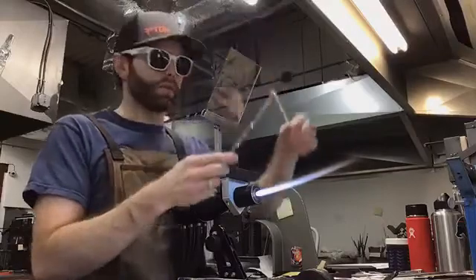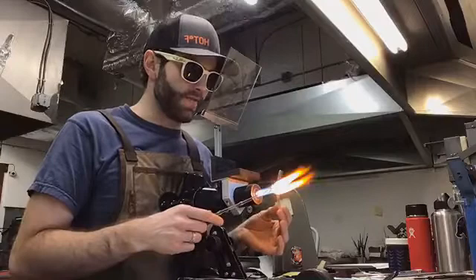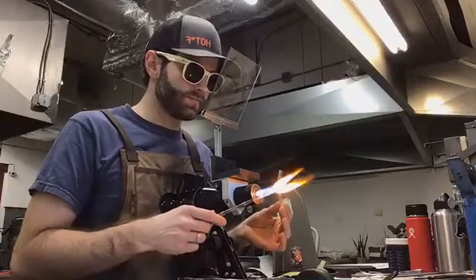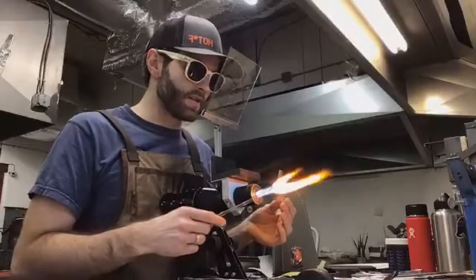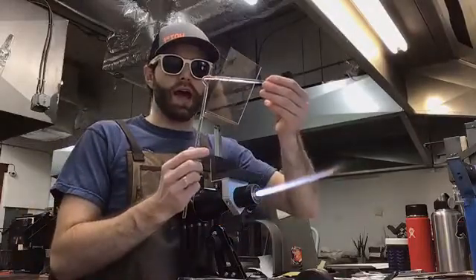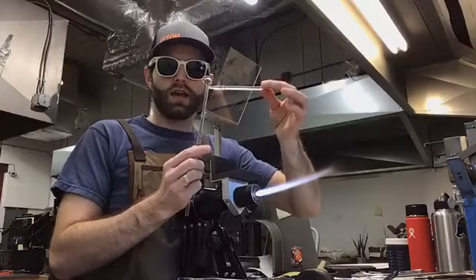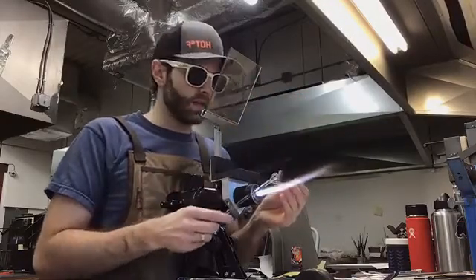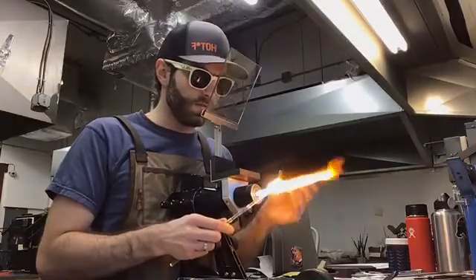Now flip it around so it's more comfortable to hold. Heat up the last little section. It's probably more like a ½ inch versus an inch. And this step's really important too. Everyone wants to just shoot it right down and stick it on there, but you actually want to pull it out first and then stick it back down to give yourself a nice open loop. Okay, and then melt this off right away while you've got that heat in there.